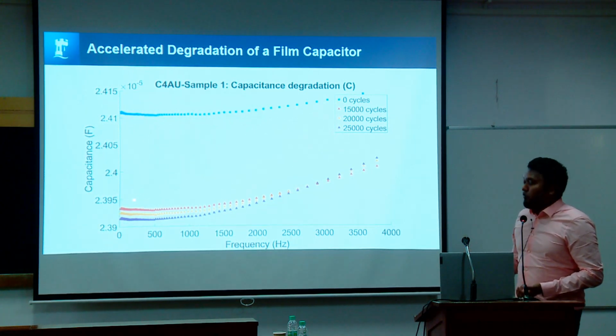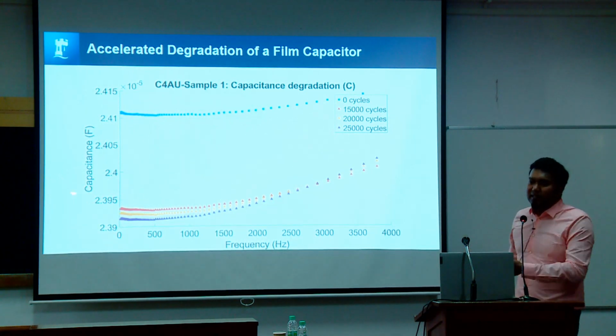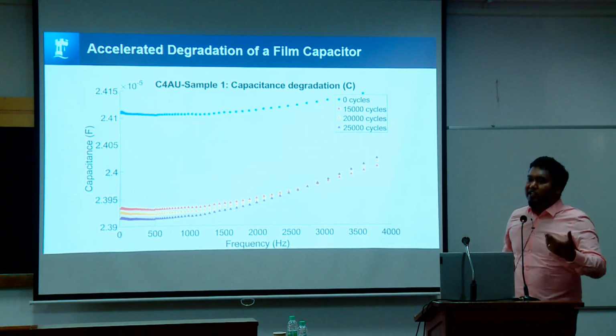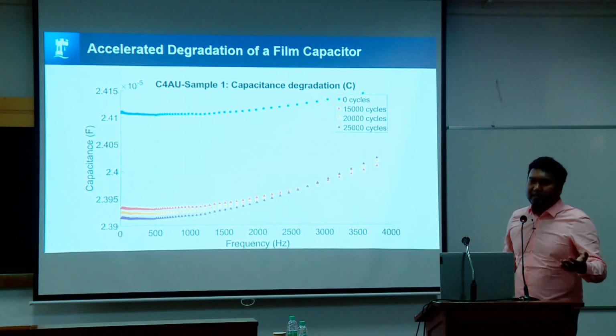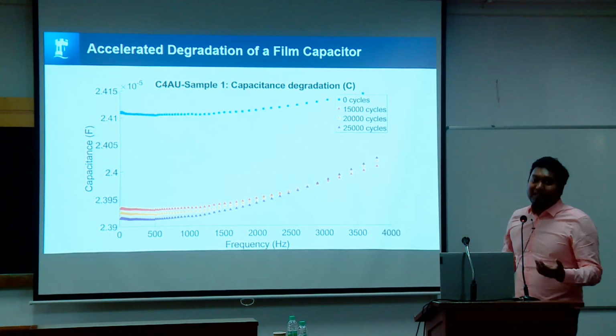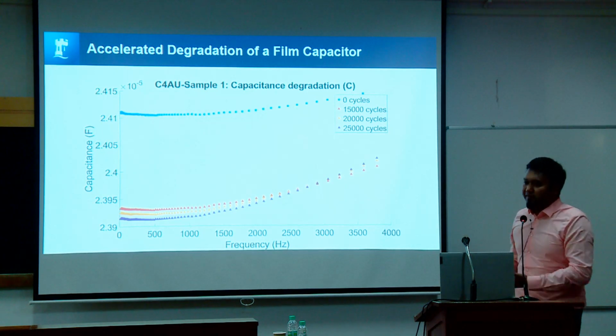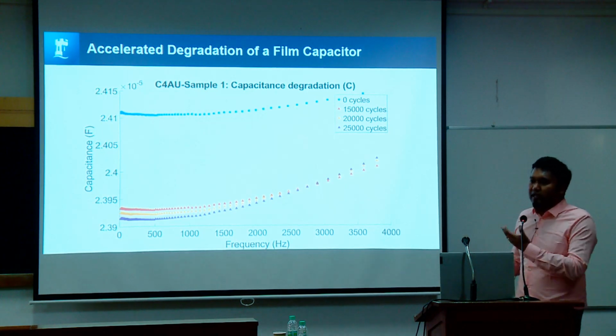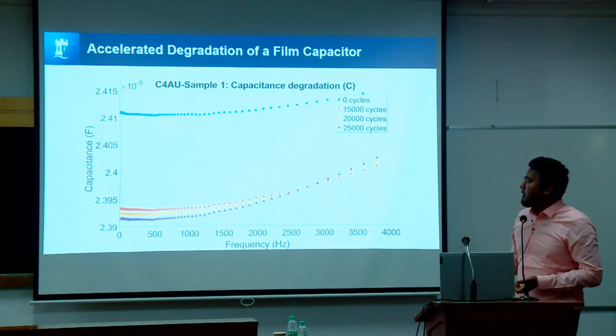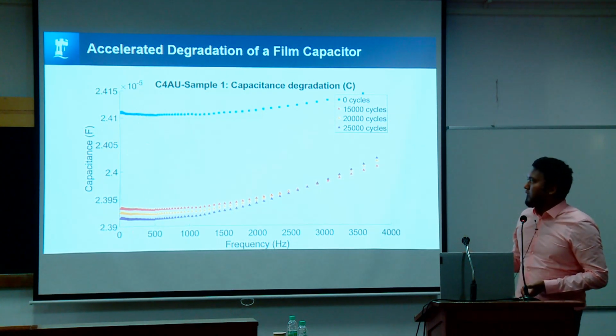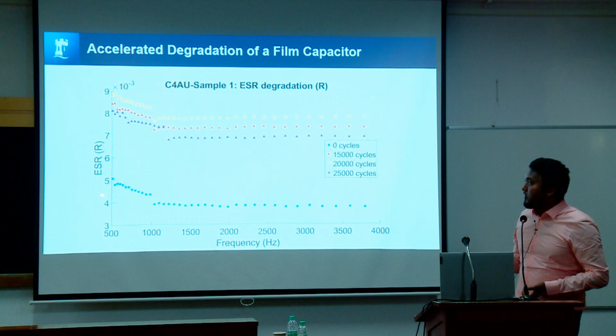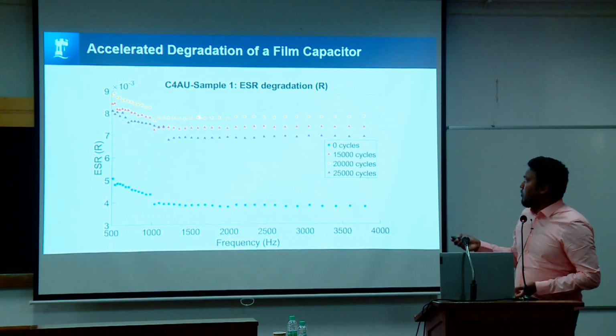The challenge with capacitors is that we can age the modules in a week or 2 weeks and they will fail, but a capacitor will take months, maybe 3 months or 6 months, to fail. So it takes a really long time to do the reliability analysis or lifetime modeling for capacitors. Here you can see the capacitance change, and here you can see the ESR change. The blue line was the initial 0 cycle, but as it cycles more and more, you can see the ESR keeps rising.